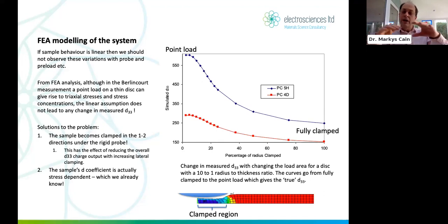We are clamping the X and Y direction that the sample wants to move when it moves up and down under stress by virtue of the geometry of the probe, which is why we suggest not using flat probes or flat punches, and it's why we suggest also using small diameter electrodes.